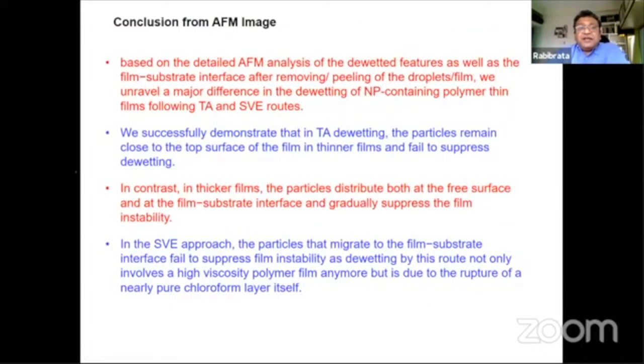I am running out of time, so here are the conclusions of the AFM images. The most important thing is particle-containing film dewetting: if you do thermal annealing, the particles go on the top of the surface. With solvent vapor annealing, the particles go to the bottom, at the substrate. This is one of the very fascinating and delicate observations.